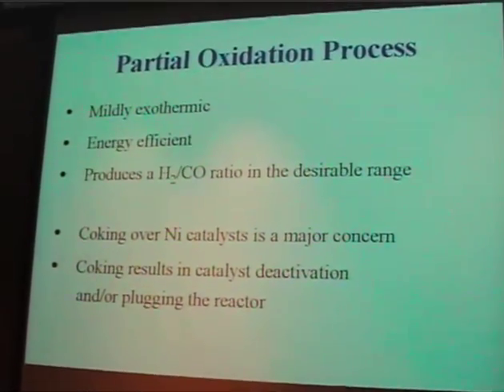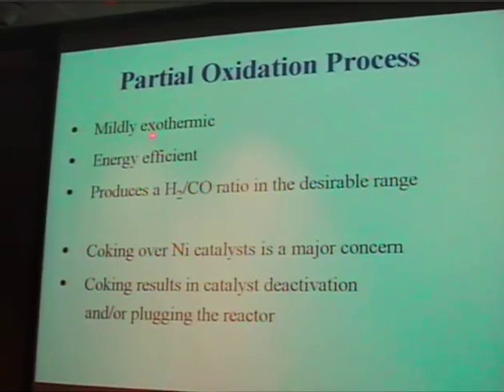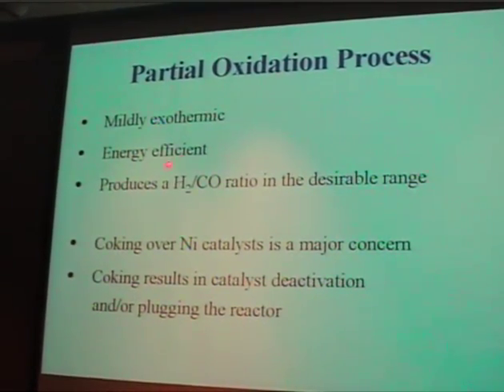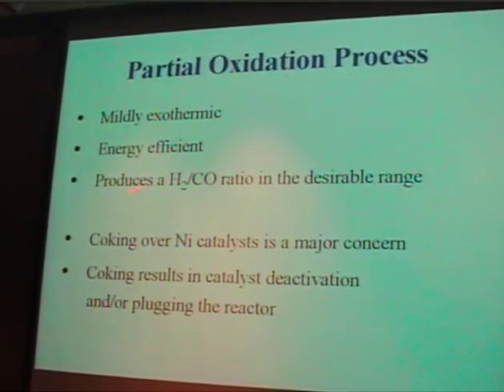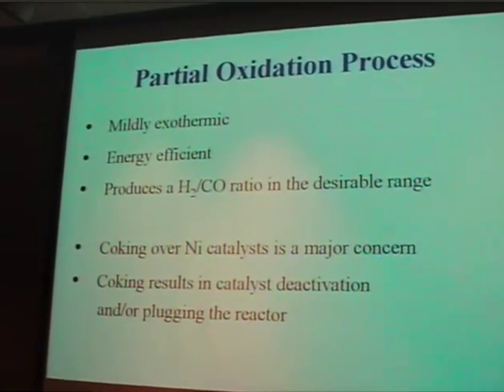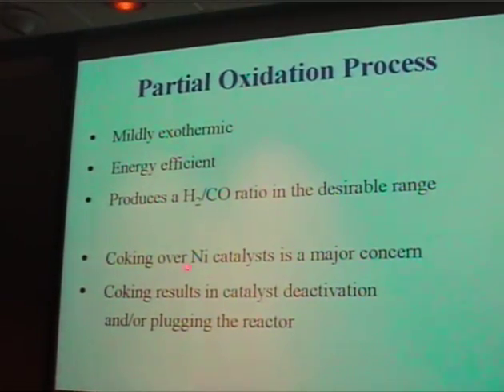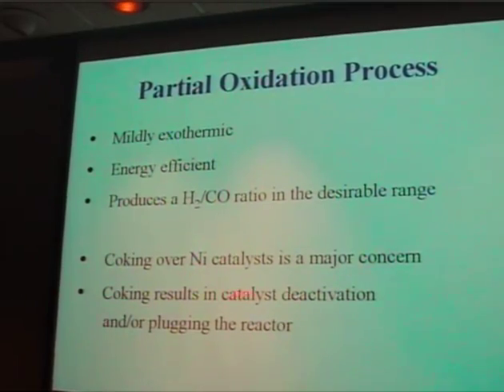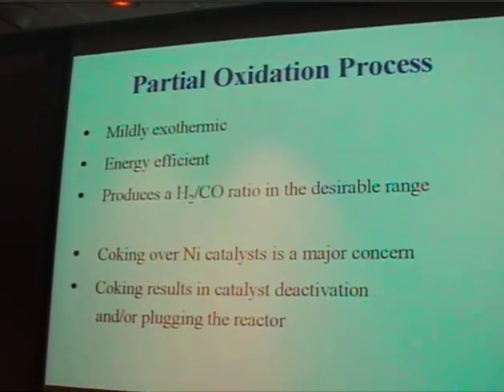We like the partial oxidation approach. It's mildly exothermic, should be energy efficient, and we get the right hydrogen to CO ratio. So our major concern was to control the coking and eliminate some of the typical problems of deactivation and plugging.